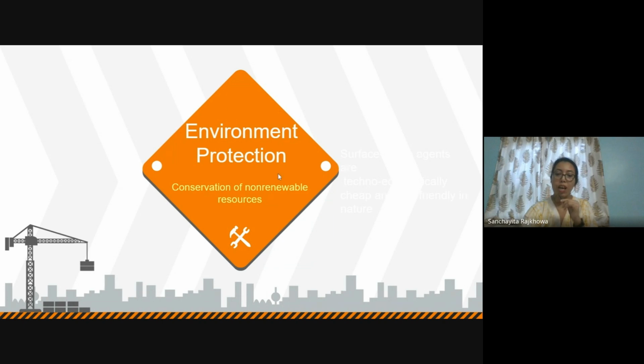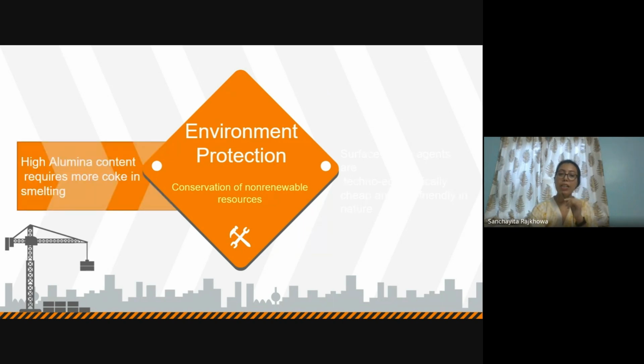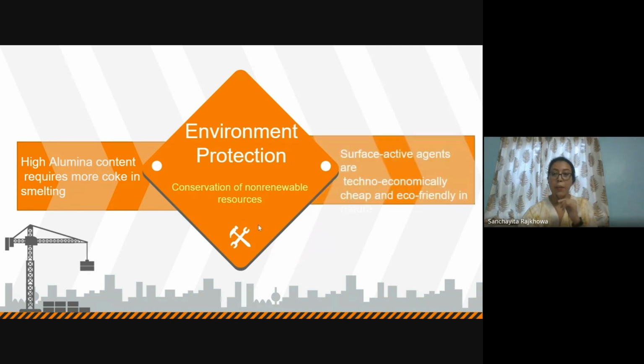Now, if we go for high alumina content ores, then it will obviously require more coke as well as more limestone during the smelting process. If you reduce the alumina content, or if you have certain processes which can reduce the alumina content as well as the silica content, then that will be beneficial to minimize the amount of resources like coke and limestone. That is one way of environmental protection.